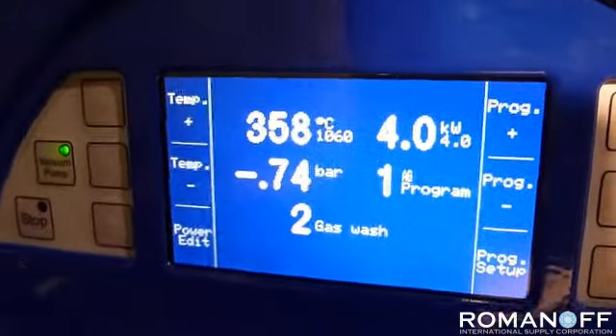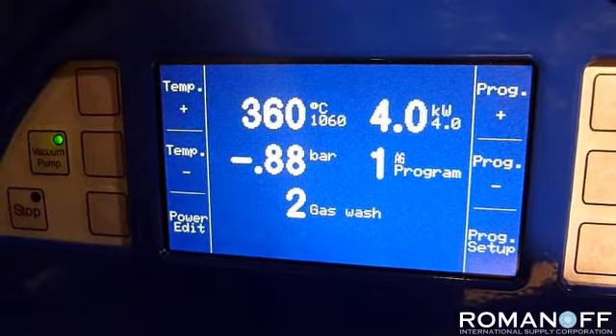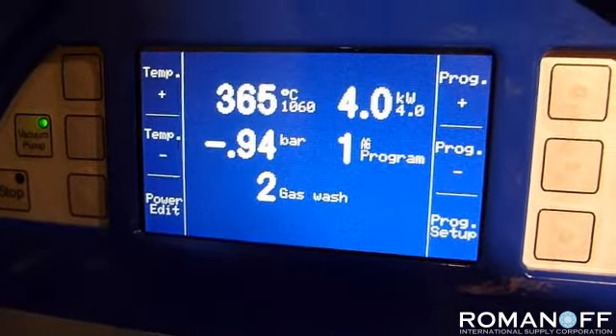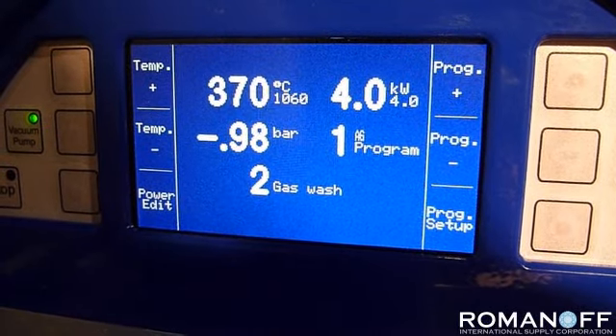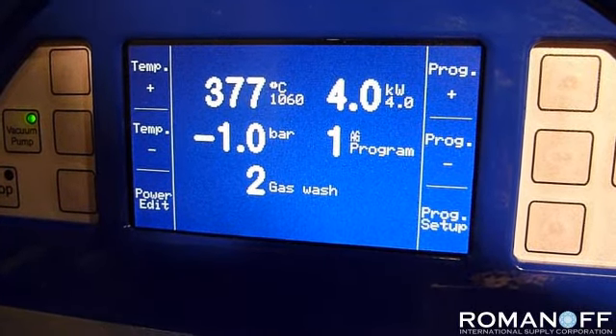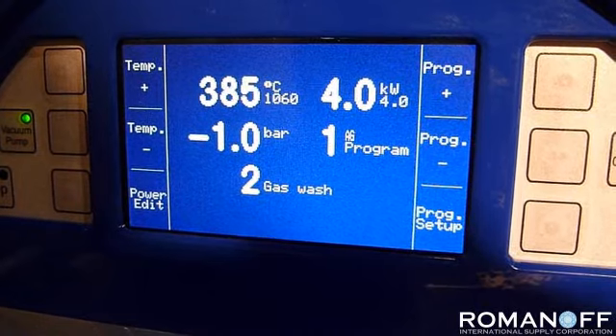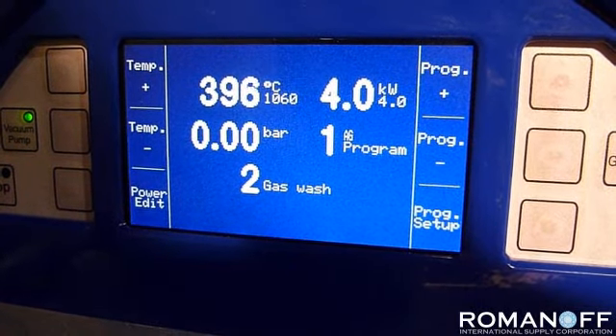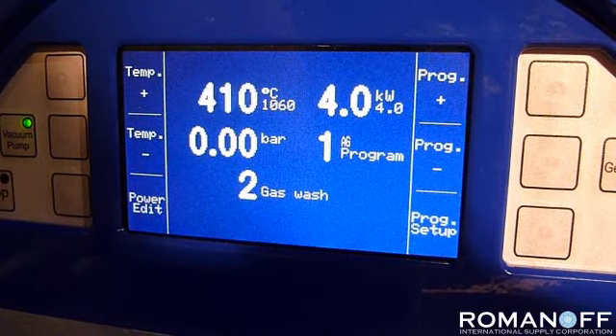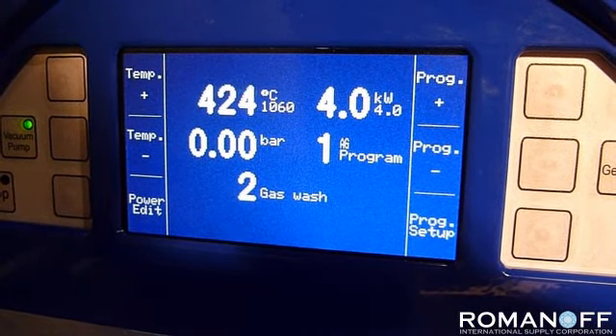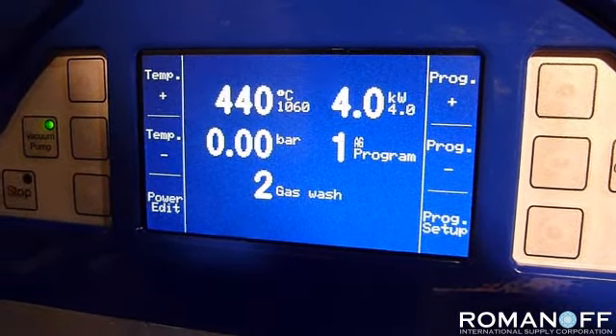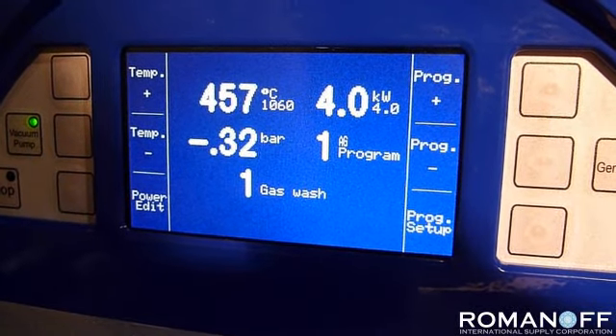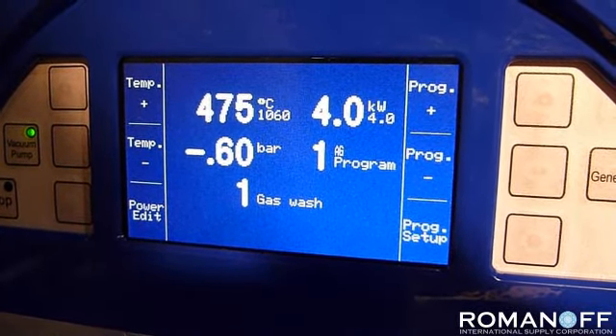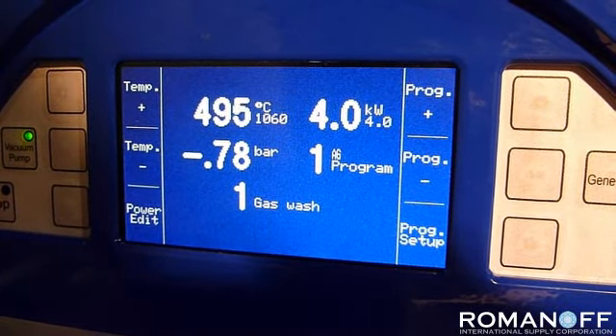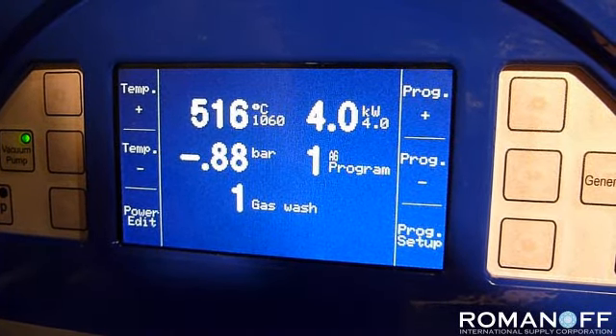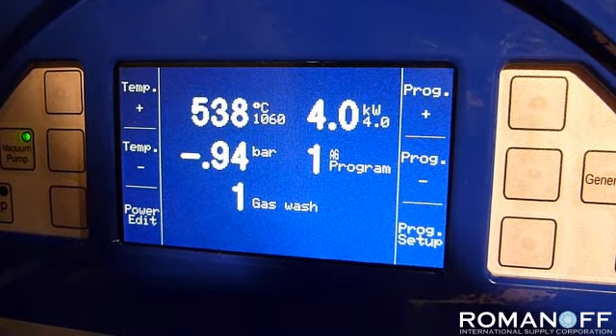We're also pulling a vacuum, as you can see it going down, so the chamber is melting the metal while it's under vacuum. It will shortly start the automatic wash cycle, which once again is introducing argon gas while the vacuum is in there. There's 2 purposes of the washing cycle. One is to keep the chamber clear of any gases that are in there, so you can fairly be comfortable that you've eliminated the gases for gas porosity. And at the same time, if you have zinc in your alloy, you need to introduce argon gas to prevent the zinc from vaporizing out of the alloy, as opposed to being under full vacuum.